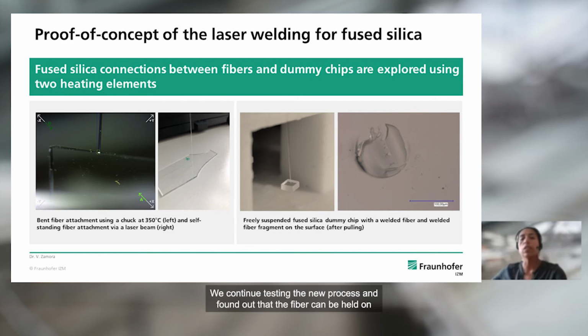We continued testing the new process and found out that the fiber can be held on a fused silica dummy chip, where the welded fragment after pulling is clear evidence of the fusion zone. Now that we have defined the welding concept for fused silica, we still have to consider the other requirements of the PICs.